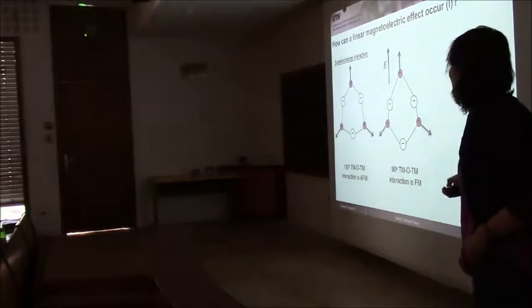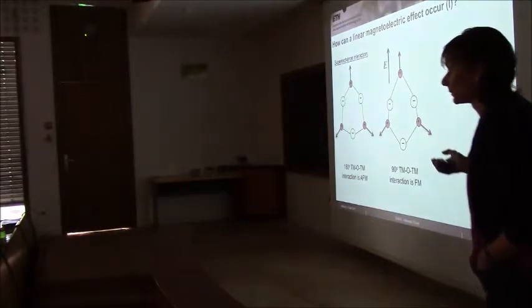So now my crystal has deformed, and here I've really exaggerated it, but look at what's happened to my bond angle. So this transition metal, oxygen, transition metal, now is much closer to 180 degrees than it started, and this one, transition metal, oxygen, transition metal, is now closer to 90 degrees, right? Just because of the deformation from applying the electric field to the positive and negative ions. And if you remember from your Goodenough-Kanamori rules, the 90 degree transition metal oxygen transition metal interaction is ferromagnetic. In many cases, of course, there are more subtleties, but usually 180 degree super exchange is antiferromagnetic, 90 degree super exchange is ferromagnetic. Right? Questions? Objections?